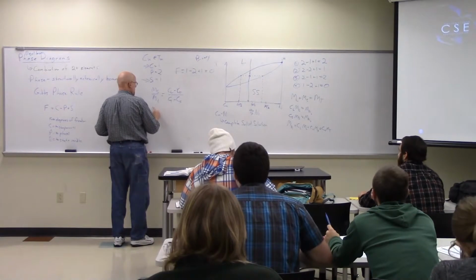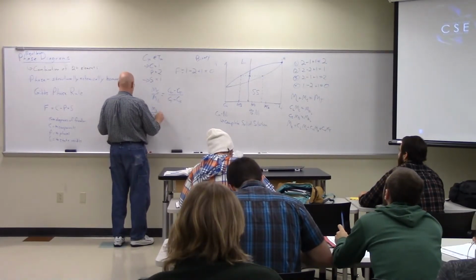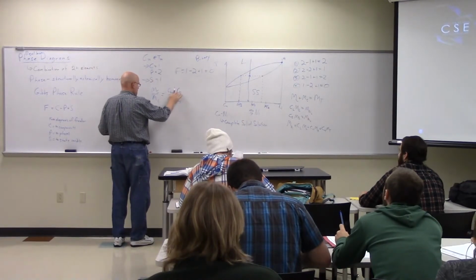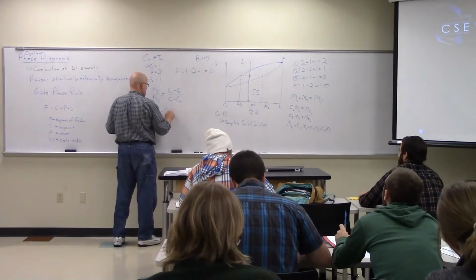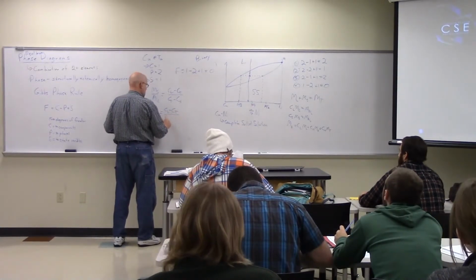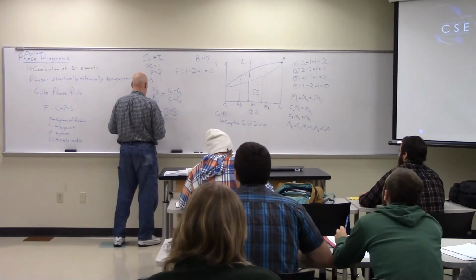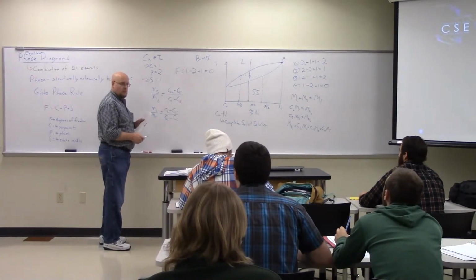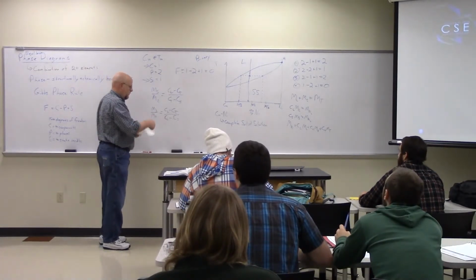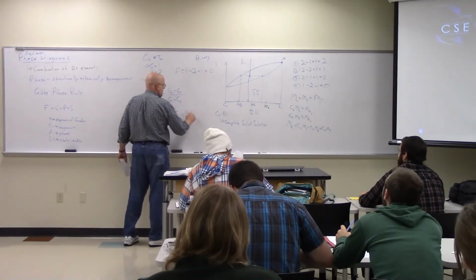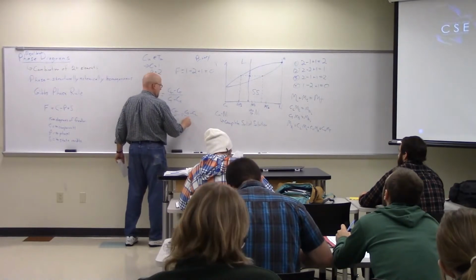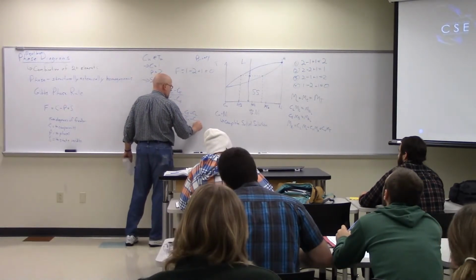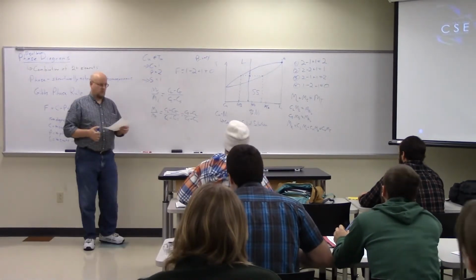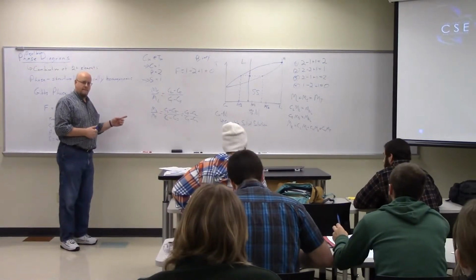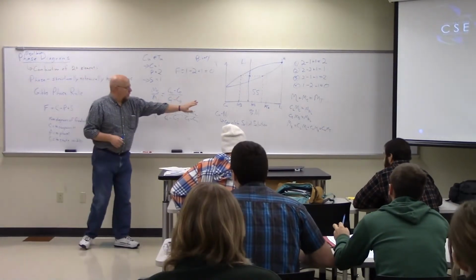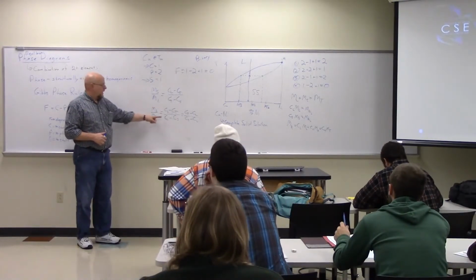So the mass of the solid divided by the total mass, if you carry this forward, again, I'm skipping steps, ends up being equal to the concentration of the liquid minus the concentration of the total, divided by the concentration of the liquid minus the concentration of the solid. Again, you're probably not going to follow because I'm leaving out too many steps. Which I can rewrite as the concentration of the total minus the concentration of the liquid, just by inverting top and bottom by -1. Okay. So using those kinds of equations to find the ratios, I end up with this expression.